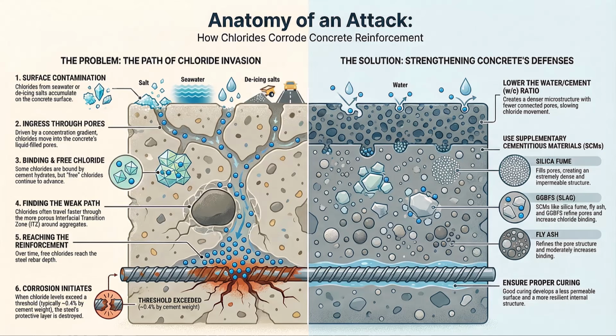So what's happening there physically? Remember, OPC needs careful hydration to build its strength and density. In high heat, water evaporates incredibly quickly. If you don't keep that concrete wet for the first 7 days, the cement paste won't fully hydrate. It leaves behind these large, interconnected capillary pores. Express lanes for chlorides. Exactly. They are express lanes for chlorides. A mix that was designed for a 5.0 coefficient quickly becomes an 8.0 material, and that guarantees the chloride threshold will be reached rapidly no matter how thick your cover is. This vulnerability makes OPC virtually unfit for purpose in these coastal zones.